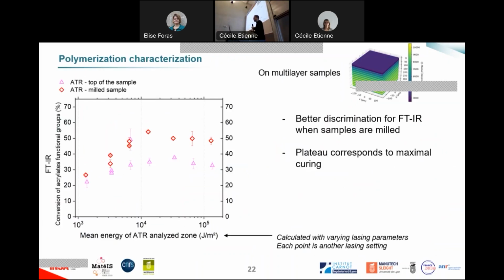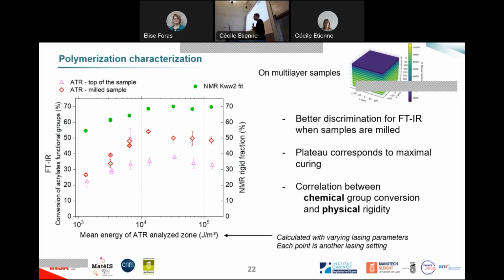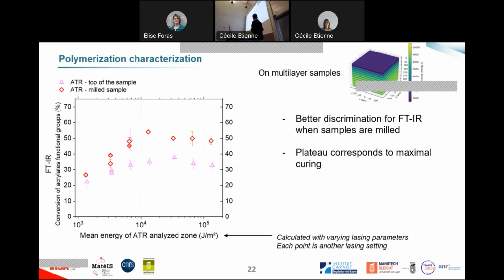So, showing you more results about that here. The results for FTIR spectroscopy give us the evolution of the conversion rate depending on the mean energy on the zone that I studied. And what you see in pink is that it increases on the top of the sample when we made the measurement on the top of the sample. And you can locate the energy at which it doesn't increase anymore.